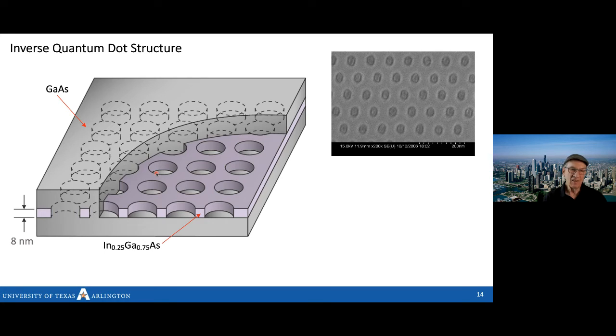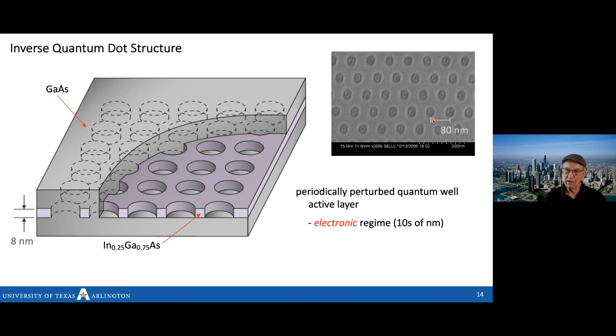The thickness of this layer is typically anywhere from 5 to 8 nanometers, and the physical size is again 30, 40, 50 nanometers, limited by the patterning. So this is a periodically perturbed quantum well active layer in the electronic regime, which is of the order of tens of nanometers.